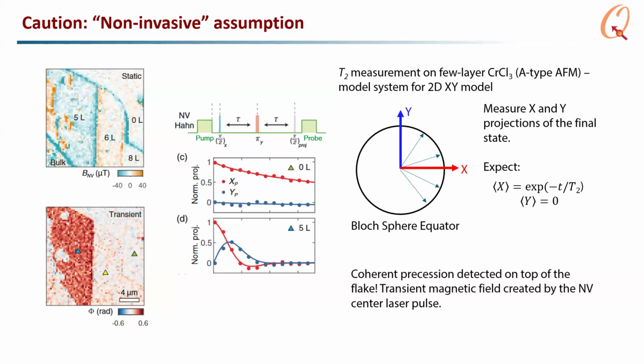So every experimental run, the precession is random. So if you average X, it should get shorter if you prepare the X state in the beginning. And that's what we see. On a region of the sample with no sample, X is decaying. But on the 5-layer region of chromium chloride, X is decaying very quickly.